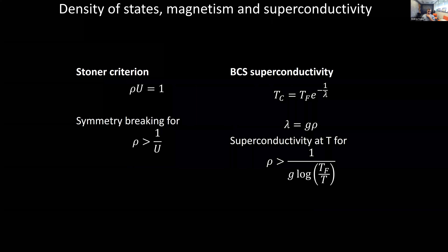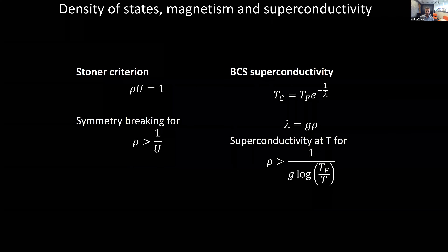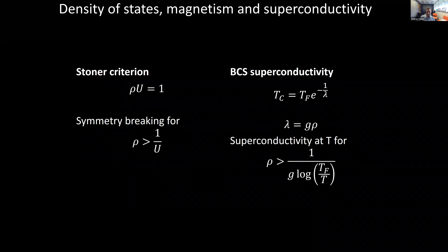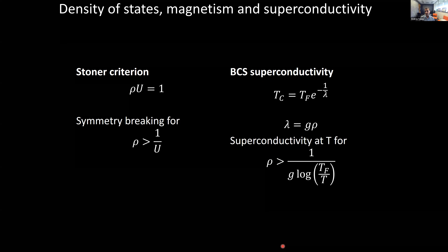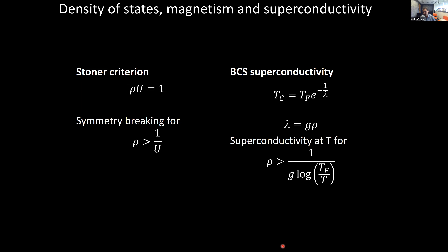The elementary thing to start with is the basic idea that density of states is good. High density of states is what you want, and flat band physics is basically coming from the fact that it's at high density of states that interesting physics starts to happen, and that's true for both magnetism and superconductivity.